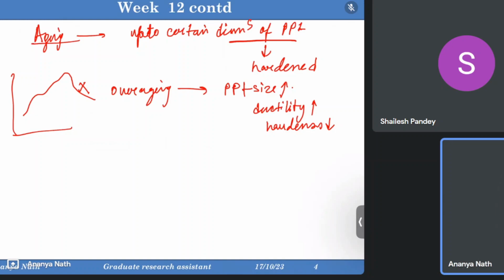So there we have only one parameter, that is the size of the precipitate, because the alloy that we are using has a certain amount of aluminium, silicon, and magnesium, and we are not externally adding any silicon and magnesium to the matrix. So whatever the amount of precipitates Mg2Si, the amount is fixed, but the size of the Mg2Si is not fixed. Up to a certain size, it will harden the material. Beyond that particular critical size, it will be overaging.